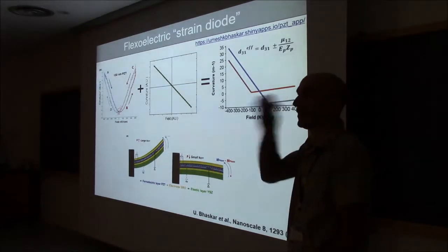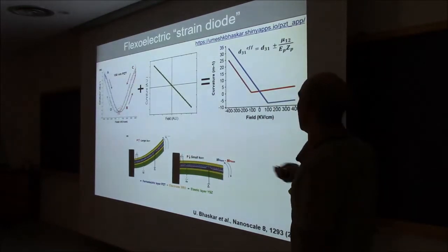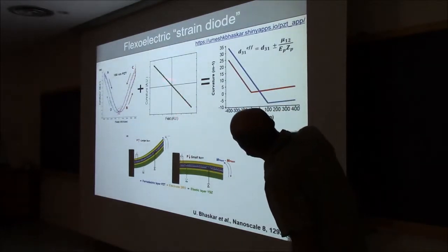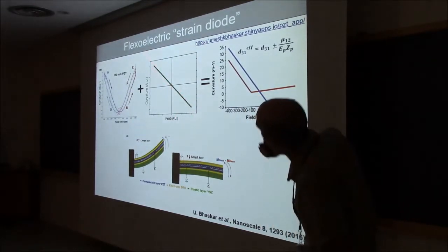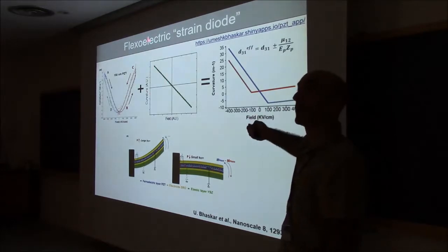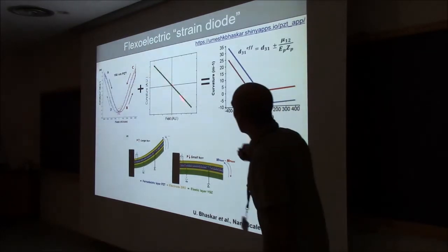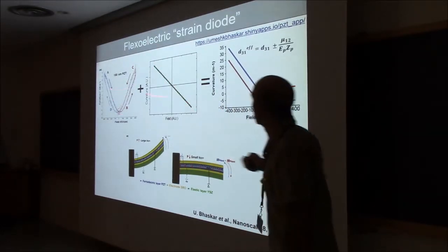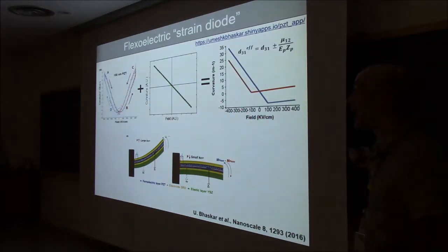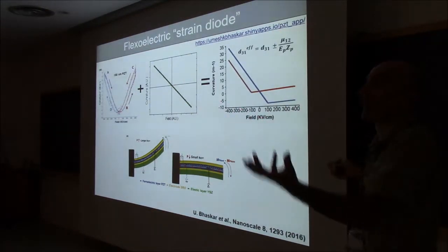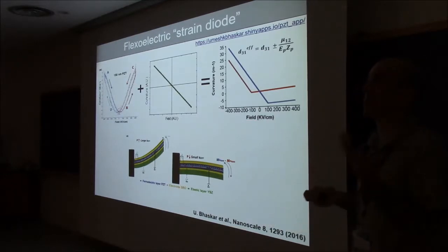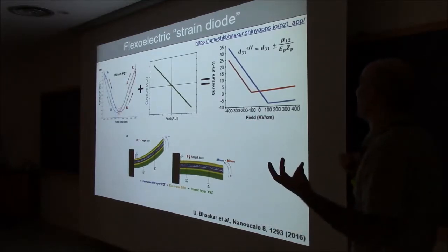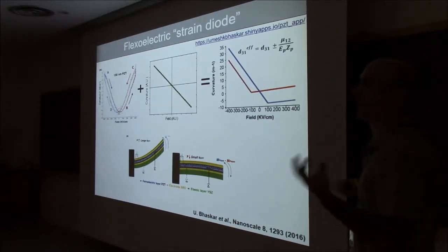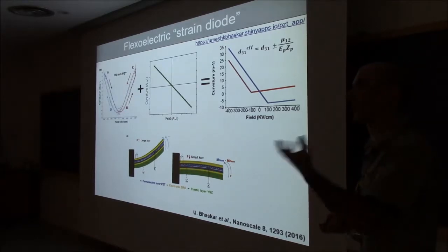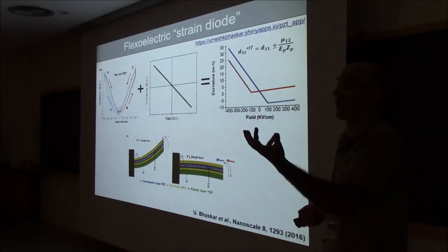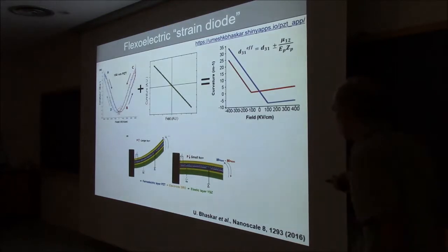The flexoelectric bending, however, is not symmetric. It depends linearly on the voltage. So if the voltage is positive, the bending will be down, and if the voltage is negative, the bending will be up. Yeah? If you add this plus this, then you should observe a completely new, qualitatively new shape of the strain versus voltage, which behaves like a diode. Okay? A lot of bending for one polarity and no bending for the other. Okay, that's the idea. This would be what one might call a strain diode.